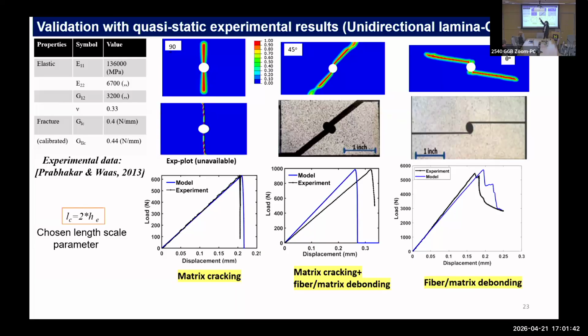Basically, remember for each dynamic case, I was showing you the local energy spectrum. I don't have the plot here, but if you look at the energy spectrum locally, you will see for this case it is the psi1, or mode 1 energy, that is driving the crack. And if it is psi1, that means it is essentially matrix cracking that is happening. Similarly, in the 0 degree case, if I look at the local energy, I see it is the psi2, which is basically the fiber matrix debonding. That is the micromechanics. So what I am trying to say is that with this approach, you not only know the crack path or the load displacement curve, you also know the underlying mechanism. Of course, in OHT you know the underlying mechanism because it is simple. But for many dynamic cases, just looking at the crack profile, you probably don't know what mechanism caused the failure or the crack path. But if you look at the energy spectrum locally, you will know whether it was mode 2, mode 1, or a mixed mode scenario.